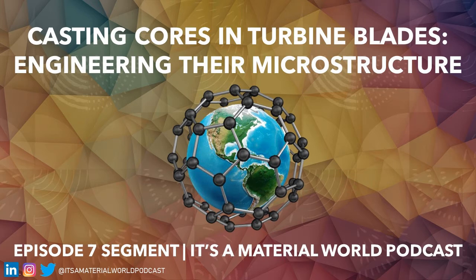And at the end of the day, the ceramic that forms the core inside of that process has a complicated pattern. They are made through a couple of different processes today. One process is high pressure injection molding, a very precisely machined metal die with a ceramic. Another process is directly printing the ceramic using 3D printing. And that is a way that is being explored on how to make those casting cores.